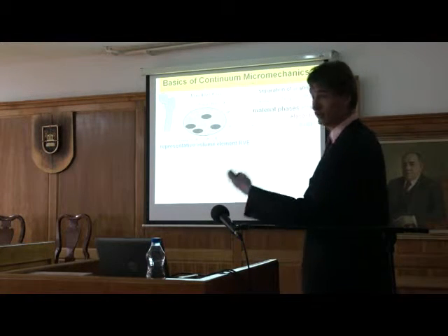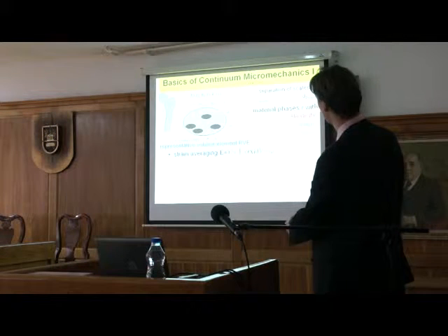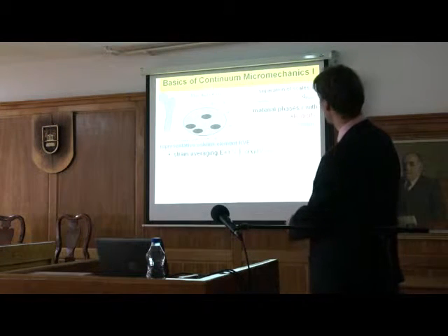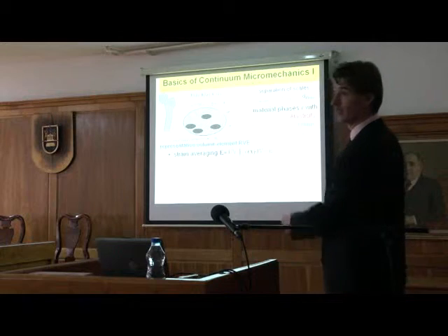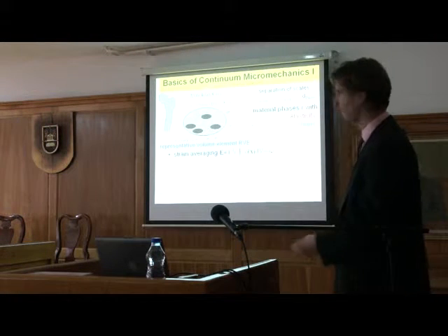Okay. And they have mechanical properties, these phases, like elasticity, strength, viscoelasticity. They have a shape and they have volume fractions. And then the interesting thing is that if this is a kinematically compatible continuum, also this volume, then the strains, the average over the microstrains in these volumes, the volume average of this is identical to the homogeneous strains put at the boundary. So it's a result of the strain compatibility. It means that this volume stays a volume, no cracks, no disintegration. So that's strain averaging, that's the first important thing.